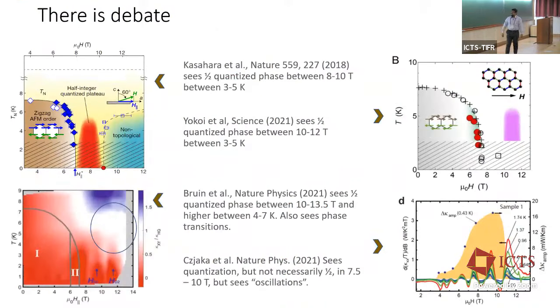But as I was mentioning, there is actually a huge amount of debate. Essentially, Yuji Matsuda's group shows that you have this half-quantized plateau, while it's moved to 10 to 12 Tesla in Yokoi's Science paper. The Bruin paper, which is the Max Planck group, says that the half-quantized plateau is at 12 or 13 Tesla, which is right here. Here is where we see this plateauing-like behavior.